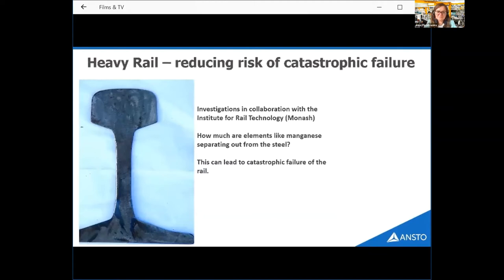Now, because it is one of the most heavily used railways in the world, new alloys are being developed for rails and wheels to allow for higher loads and greater transport efficiencies. Manganese is commonly used to increase the strength of steel, and a little bit of it improves strength, but the higher the manganese concentration, the more brittle it is too. And it can also make welding more difficult.